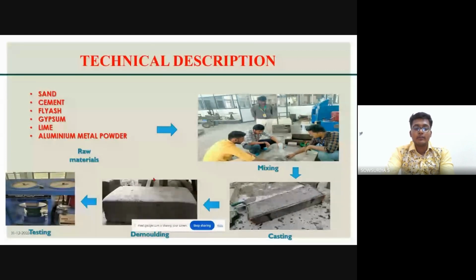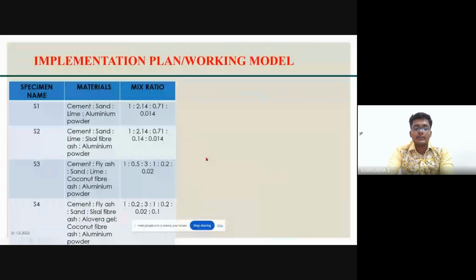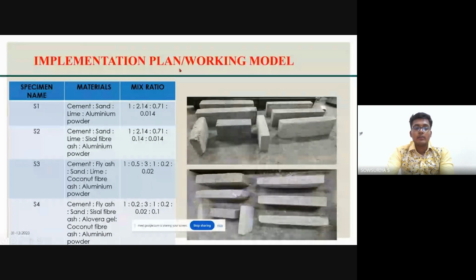After mixing, we have to cast the lightweight panel. And after casting, the next process is demolding. After the demolding, the process is testing. And this is the working model. In the working model, we use 4 ratios. In specimen 1: cement, sand, lime, aluminum powder, and the mix ratio is 1 to 2.14 to 0.71 to 0.014. And in specimen 2, the choice is cement, sand, lime, aluminum powder, and sisal fibers.